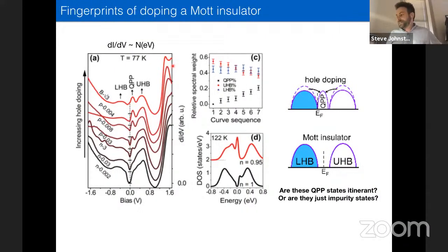So, fast forwarding through a lot of history, Hanno's group tried this for many, many substrates and for many, many years, and they were finally successful in 2017. So what I'm showing here is STS data, scanning tunneling spectroscopy data, taken on a series of monolayers grown on substrates with increasing boron doping levels. Okay. So here, this is indicating the dopant type in the substrate and the resistivity of the substrate. So increasing along this direction corresponds to increasing hole doping in the tin monolayer due to increased dopants placed in the silicon substrate. So STS, this is basically dI/dV, so you can think of this roughly as the density of states of the system that's being probed.